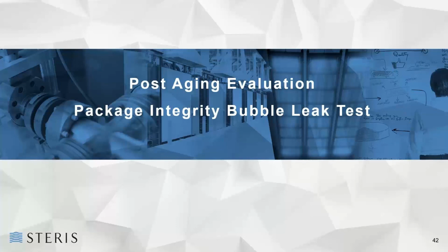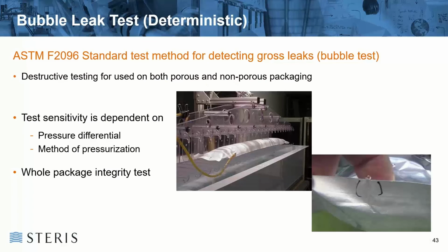One of the last tests I'm going to talk about today is bubble leak testing. It's probably one of the best tests that I believe in. Again, it's a deterministic test, and it basically tests your whole package. And by whole package, I mean it tests the surfaces and the seals, not just the seals like the previously mentioned standards. The problem with it is that test sensitivity is only down as far as 250 micron, a defect of down to 250 micron. But again, that is negated by it being a whole package integrity test.